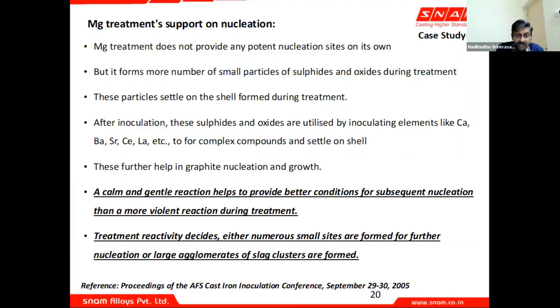Now, when we have a lesser percentage of magnesium and a higher percentage, in absolute terms, compared to a high magnesium, low TRE, a slightly higher TRE and calcium and a slightly lower magnesium, that provides a calm and gentle reaction, which gives better conditions for subsequent nucleation. When there is a lot of violence, there is going to be a lot of turbulence, oxidation taking place, naturally a lot of dross and slag formation. So with this sort of a combination, we are able to provide a gentle and calm reaction.